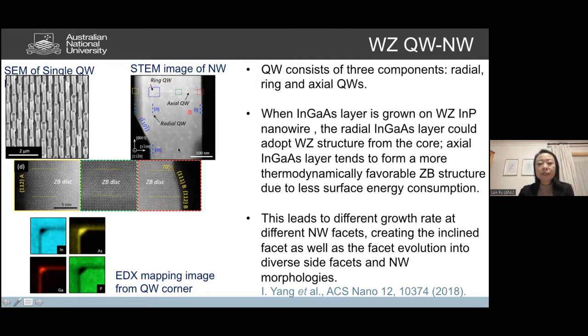So I won't go into the detail. You can see this paper, where we have a very detailed analysis of the crystal structure. We're also trying to understand how the morphology changes that leads to that. What we find is that when we have the indium gallium arsenide grown on this wurtzite-based indium phosphide nanowire, what happens really depends on which facet the material is formed on, and then you form different crystal structures.